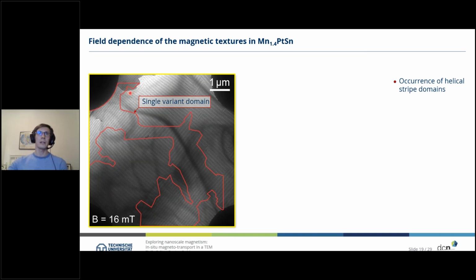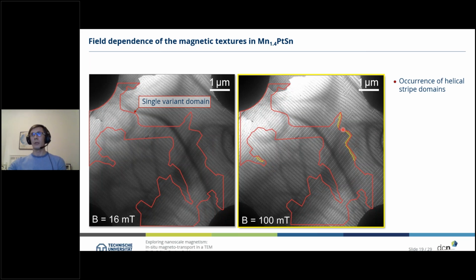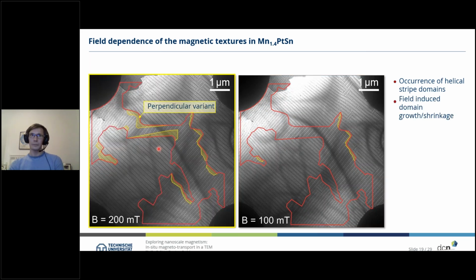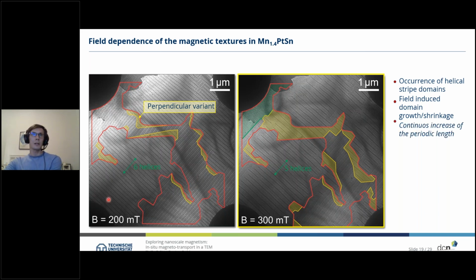So starting at low magnetic fields, we see different variants of these helical stripe domains. If we increase the magnetic field, some of them are growing, and growing even farther in one direction. But what is also obvious is that the spacing of these stripe domains is changing when we compare, for example, 200 and 300 millitesla. There's a larger spacing at 300 millitesla.